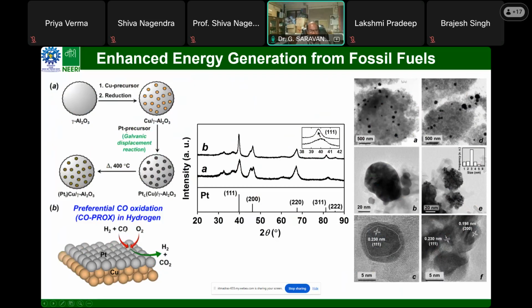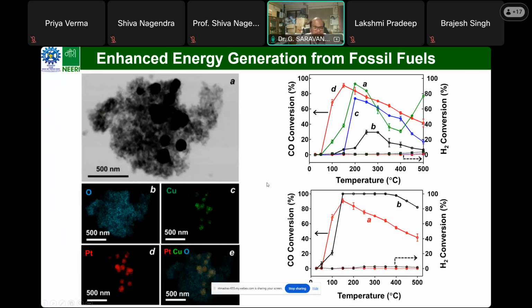This is the reaction that we targeted: hydrogen and CO are mixed, and in the presence of oxygen, the CO should be converted. We tried various characterizations, and this is the typical CO conversion. This is the commercial platinum. This one, the core-shell structure, shows selective CO removal even below 50 degrees. This is the hydrogen concentration up to 300 degrees.